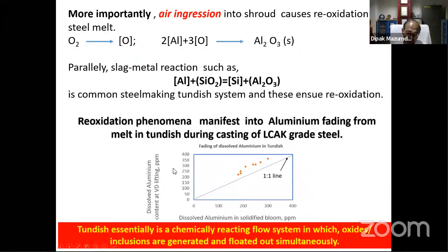And as you can see here, I have plotted the industrial measurements, which show that the VD lifting aluminum content is higher than the dissolved aluminum content at the solidified bloom. This axis is 0 to 400. This is the 1:1 line. The points which are above the line essentially imply that we have more dissolved aluminum at the VD lifting station than at the solidified bloom, which essentially means that aluminum has undergone fading in the Tundish, or dissolved aluminum is removed from the Tundish itself.